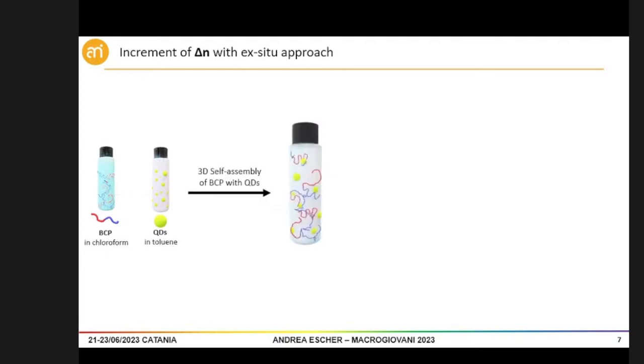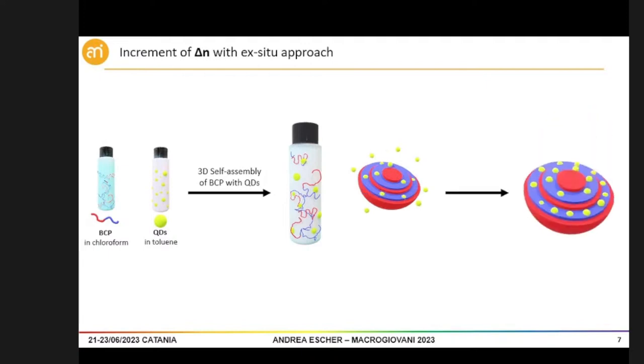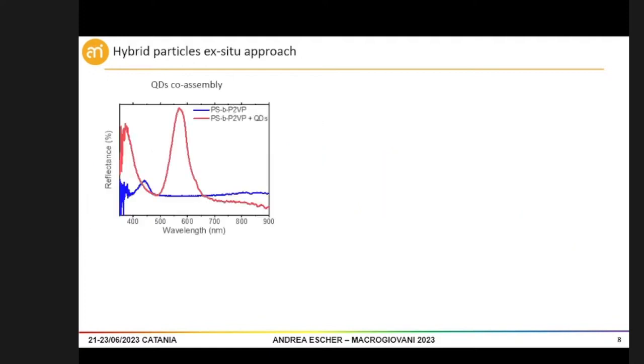The second case is called the increment of dielectric contrast by ex situ approach, and we start with a solution of block copolymer in chloroform and another solution of quantum dots, in this case in xylene or toluene. We mix together by emulsion process the two solutions, and we can obtain also in this case photonic pigments with quantum dots inside.